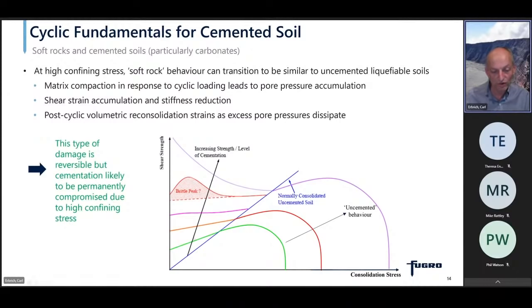So as we move from this sort of dry side of the critical state to the wet side of the critical state, we find that we gradually move into more and more fragile, brittle behavior, which doesn't look in many respects that dissimilar to soft clays. You know, we've modeled calcarenites with modified Cam clay on the wet side of critical before.